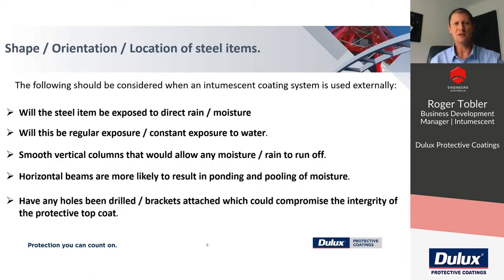And lastly, consider, have any holes been drilled, brackets mounted? Has there been any welding? Has the integrity of the top coat been compromised? And when the integrity of the top coat is compromised, the intumescent is now potentially exposed to moisture. Unless it's an epoxy intumescent, solvent-based and water-based, they can be damaged by moisture.